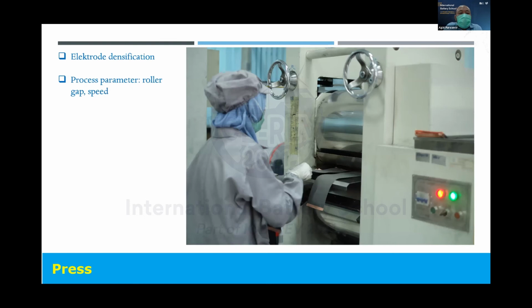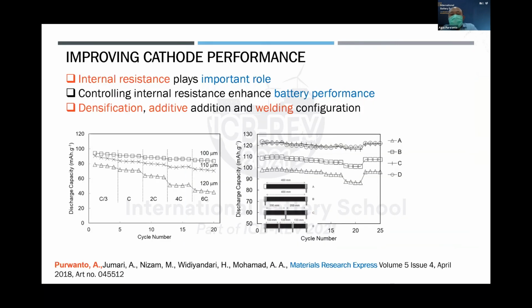After that, we come to the electrode densification. The electrode densification uses a pressing machine. The parameters of this process are roller gap and also speed. The electrode densification is important to control the performance of the lithium-ion battery. And here I show that different densification will produce batteries with different internal resistance. Internal resistance is one parameter of the lithium-ion battery which affects the overall performance of the battery.